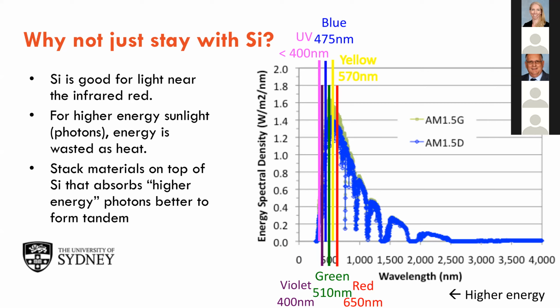And yes, you can absorb high photon energy, but the voltage of the solar cell is still very low. So for example, for a silicon cell, the output voltage of the cell is around 0.6 V. So you can have higher bandgap materials. For example, if you have a bandgap of 1.5 eV, and it's a direct bandgap material, the output voltage is around 1 V, so it gives you a higher voltage. So what can you do with these different kinds of materials?